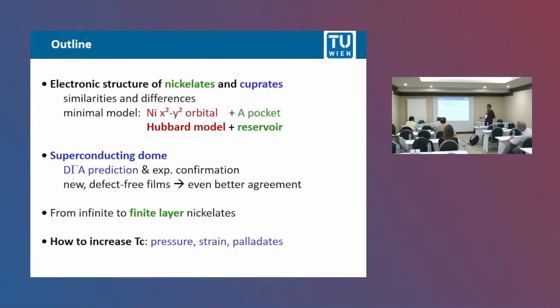And this prediction has now been experimentally confirmed with breathtaking accuracy, much better than we had expected. And that is thanks to new defect-free films. I will briefly discuss it. I will then also show that finite layer nickelates nicely match into this overall picture, and if time allows at the end, discuss how to increase TC, for example, by using pressure, strain, or palladates.